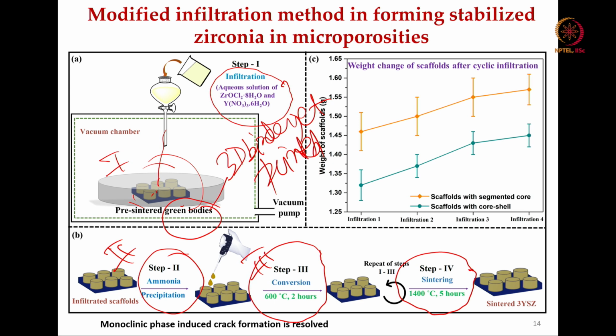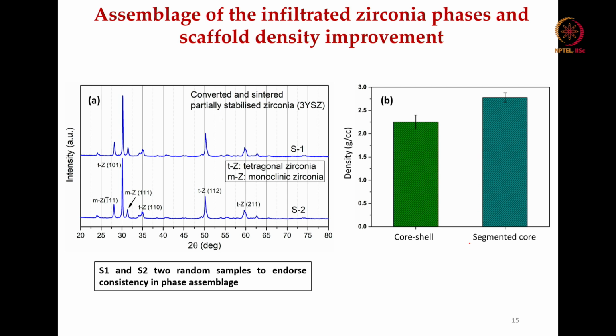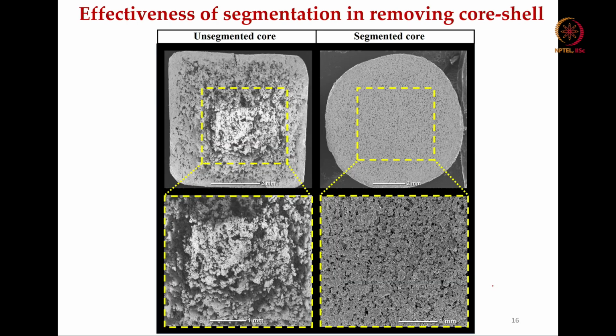What we can see is that after multiple iterations of step 1 to step 3, we are able to get sintered zirconia. You can very clearly see that TZ is essentially tetragonal zirconia, MZ is monoclinic zirconia, and S1 and S2 are essentially 2 random samples to endorse consistency in phase assemblage. Density wise it is fairly low, close to 3, and zirconia density, as you know, is 6.1 gram per cc. So, it is much lower than that, almost like 50% porosity.